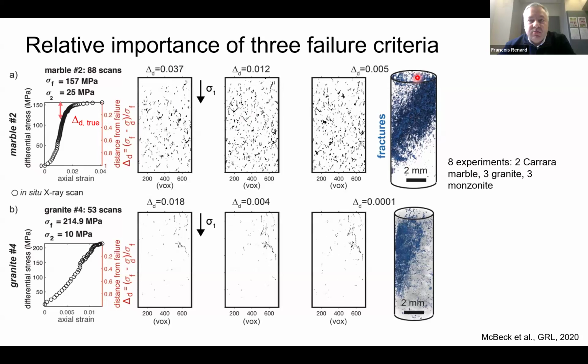And this image is a 2D slice in the sample. So every little black object is a fracture. And the fractures are growing until the sample fails. What we want to predict here is the distance to failure. So for a given sample, like this one, can we predict how far it is from failure? What is the proximity to failure? Is delta equal to 0.5, 0.3, 0.01? So we did the same. We extracted all the fractures here.